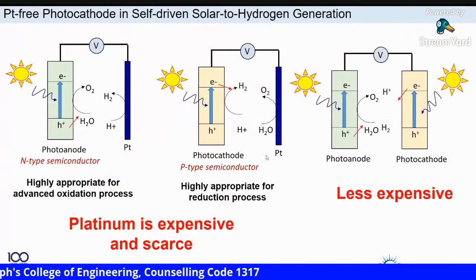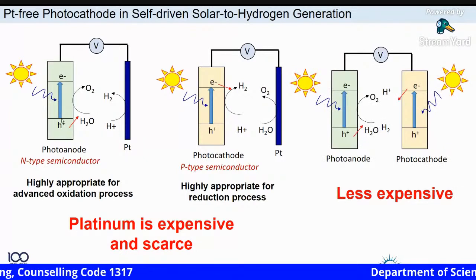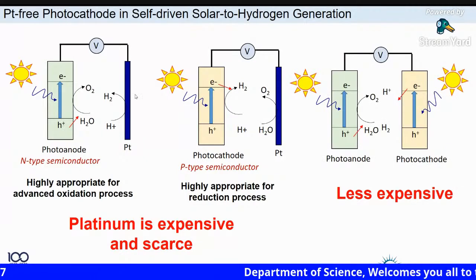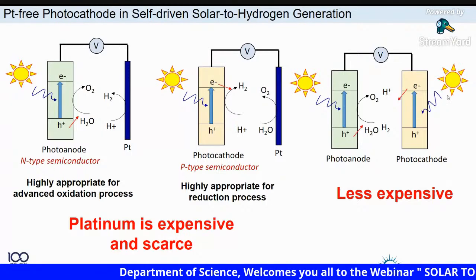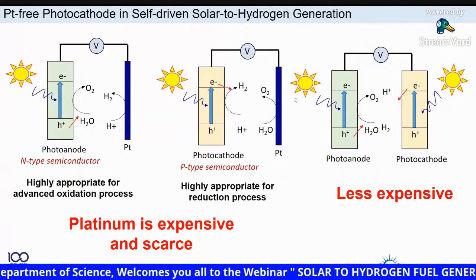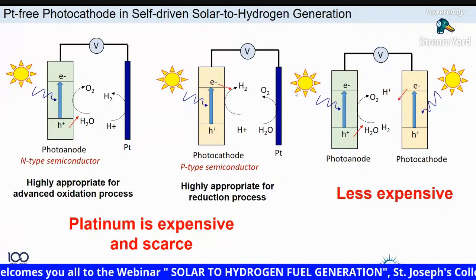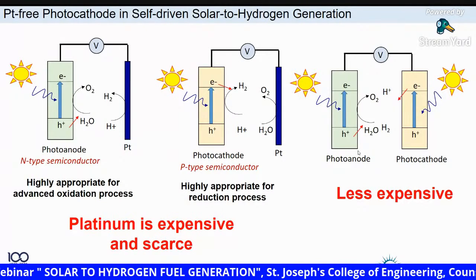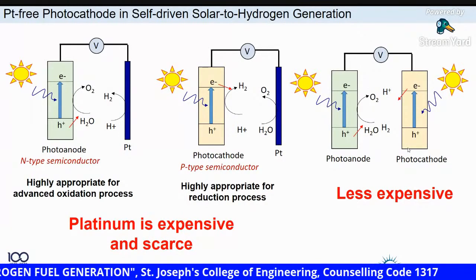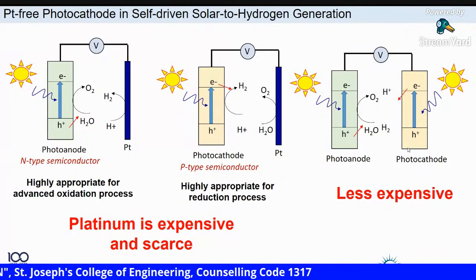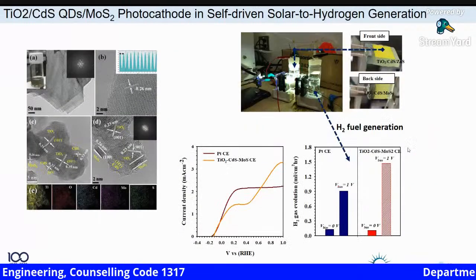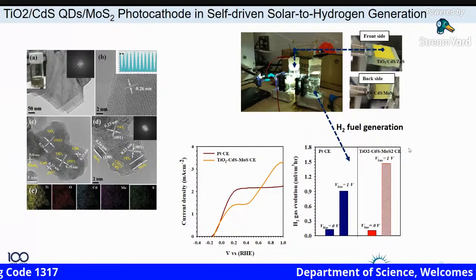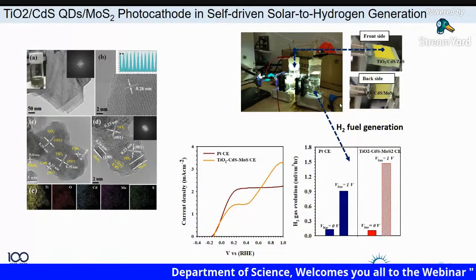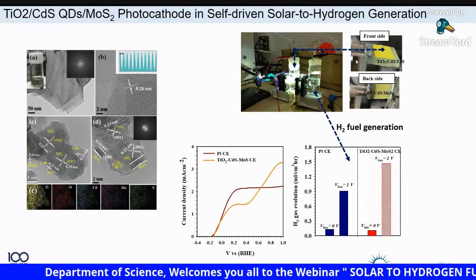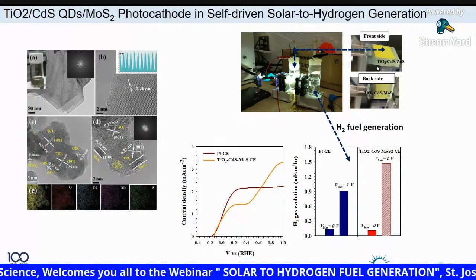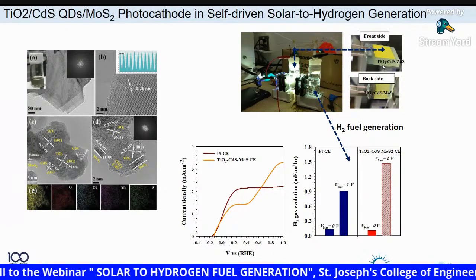Otherwise, you can keep the photoanode and just replace the platinum. This is the novel idea. You can completely replace the platinum in the water splitting cell with photoanode and photocathode. So it's a cheaper one. And from this point of view, we reported a few years ago, and you can see the photoanode on the front side and the photocathode on the back side. It's like a sandwich structure.